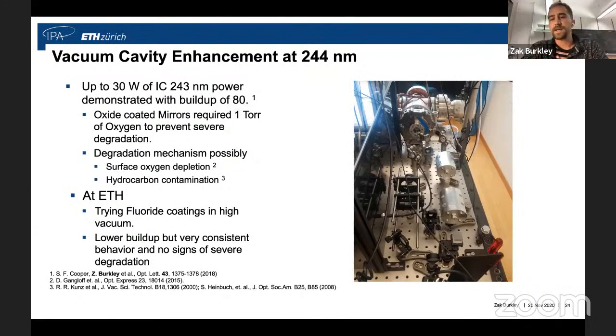And I don't see any signs of severe degradation or photocontamination when I go to high vacuum. And I think we've seen maybe 5 to 10 watts of intracavity power at high vacuum with these calcium fluoride mirrors over a couple hour time scale, and we don't think they're degrading. As you've seen, actually, the thing that's degrading are these optics outside of vacuum leading up to the cavity. Very good. All right, we have a couple of questions from our panelists.